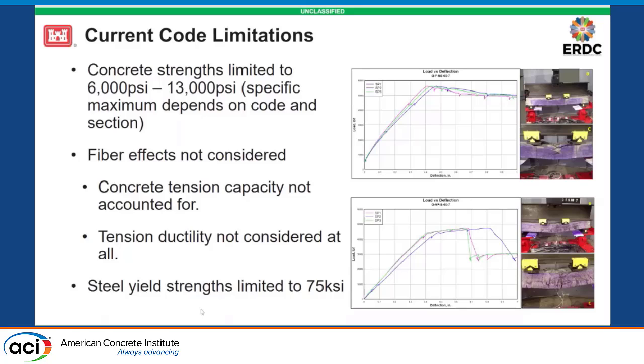Potentially more important is that fiber effects are not considered. The fiber allows for significant tension to be created in the concrete, and also a significant amount of ductility. In order to highlight that, you can see over on the right I've got two sets of tests. These are identical test specimens, other than the fact that one of them has fibers and the other one does not.